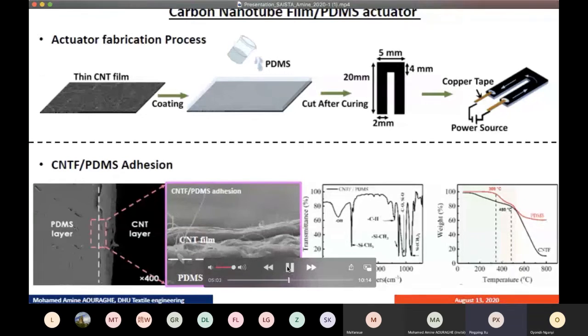First of all, we have coated CNT film with different thicknesses of PDMS layer and cut it into a specific shape as shown in this figure. Finally, we soldered copper wires to both edges of the U-shaped composites, and we applied direct current to activate actuation. Due to the porous structure of CNT film, the PDMS polymer penetrates and adheres well to the CNT surface as shown in the SEM figure.